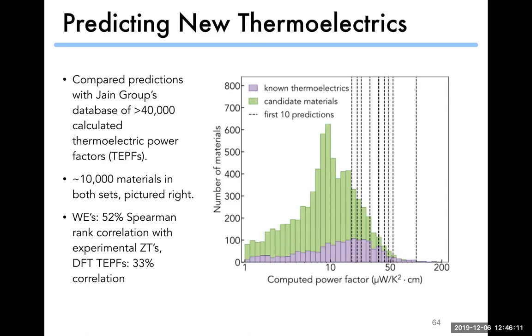And when you actually plot the power factors for the materials that our model is suggesting, we found that the top 10 were not only better than just the large number of calculations that they'd done, the average thermoelectric power factor, but also the average thermoelectric power factor of known thermoelectrics. So these are materials that the Jain group had made a calculation for, but that had never occurred in the literature. So this was a promising result, but we wanted to see,